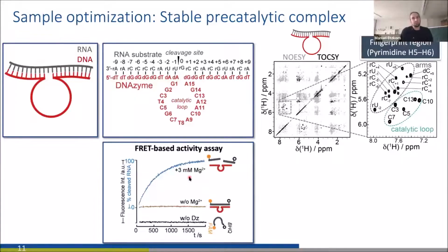So this shows homonuclear correlations of this DNA-RNA complex in the absence of divalent metal ions, and you can see that the spectral quality is quite good. In the following, I would just focus on this region here, which we call the fingerprint region, because it is nicely dispersed and nicely separates the peaks from the arm region and from the catalytic loop region.